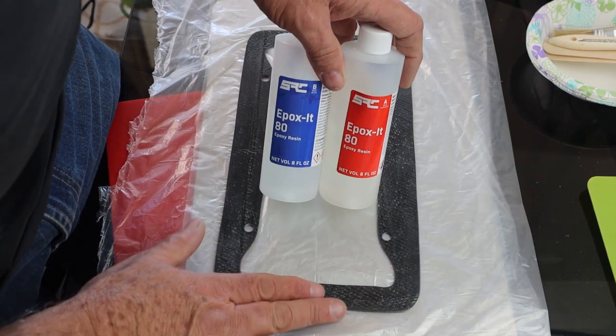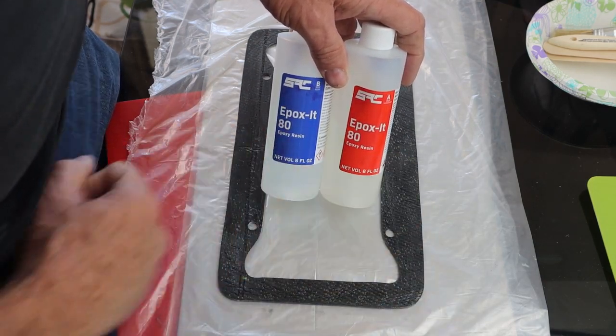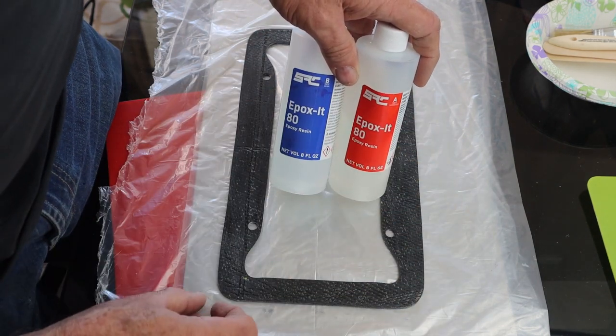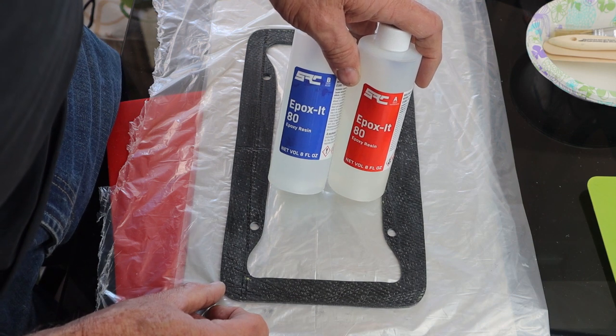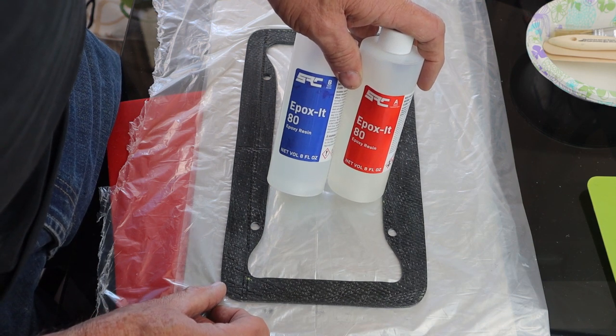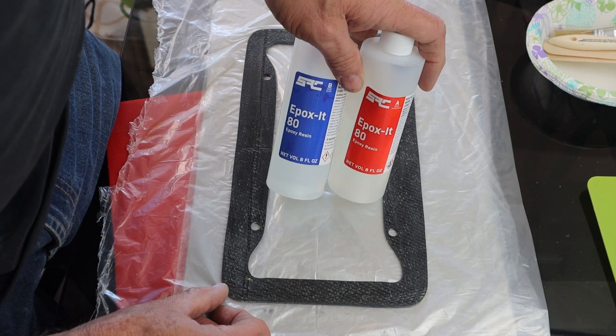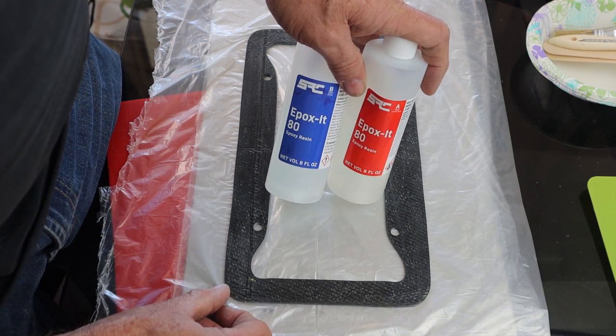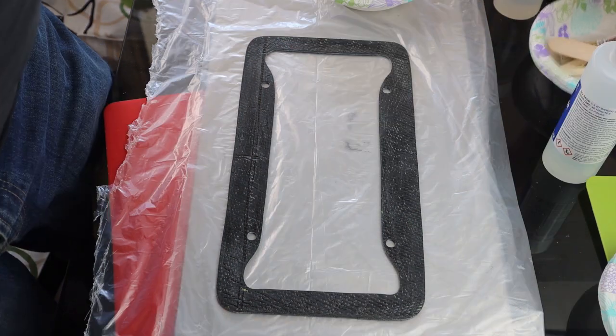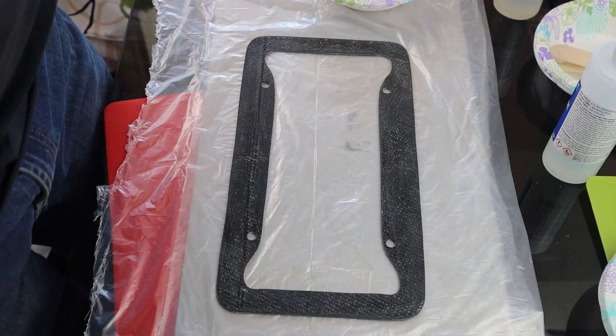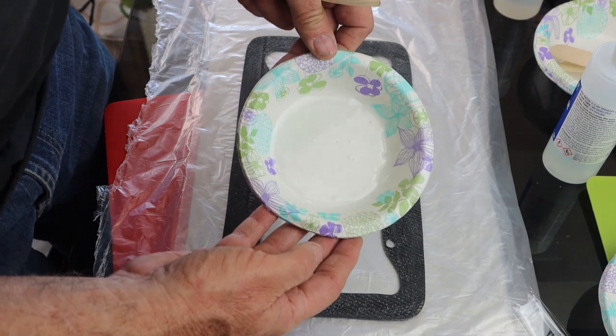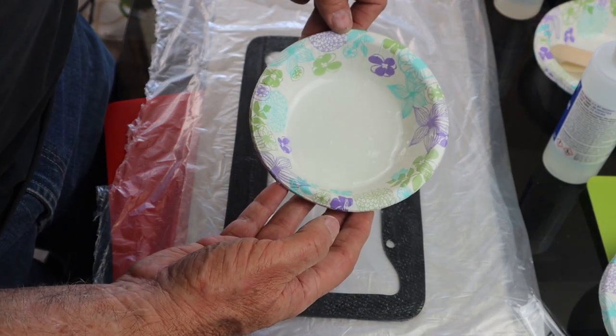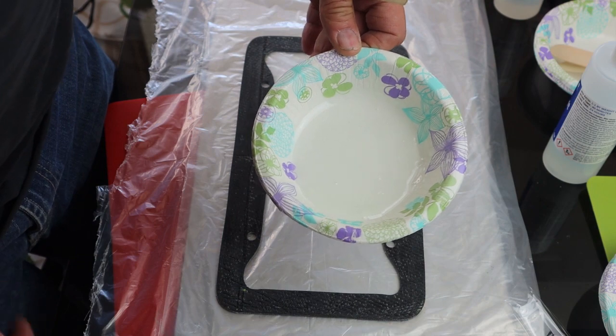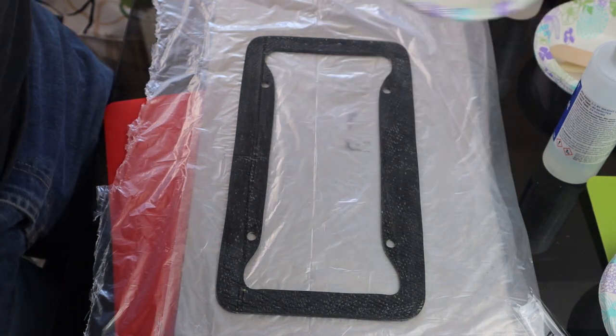The other reason is once you put this resin on the license plate, it's going to self-level, so it's going to become very smooth. And then when we put the first coat down, we're going to hit it with the heat gun to burst any bubbles. You don't want any bubbles on the surface. So let's go ahead and mix up some resin and apply the first coat of resin to the license plate. We've mixed up 20 grams of resin, 10 grams of part A, 10 grams of part B. Now we're going to apply the first coat of the resin to the license plate frame.